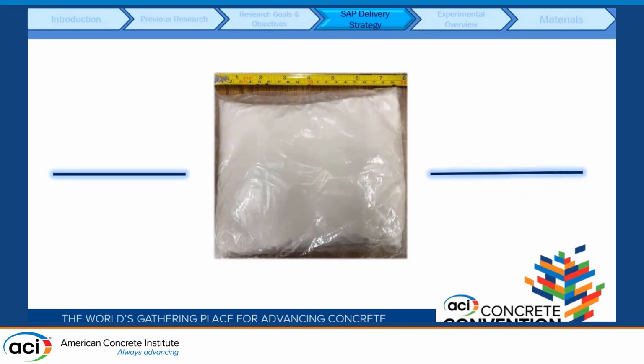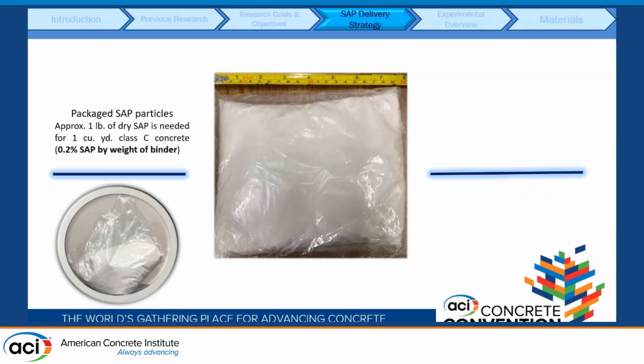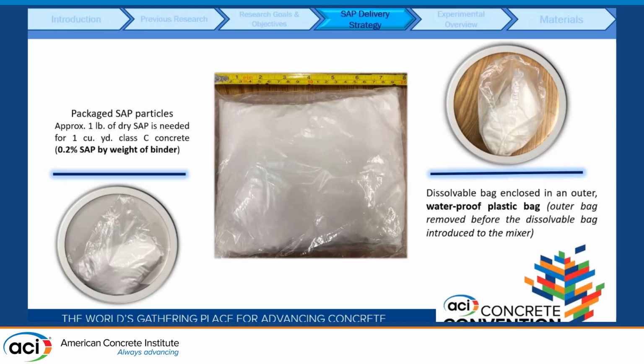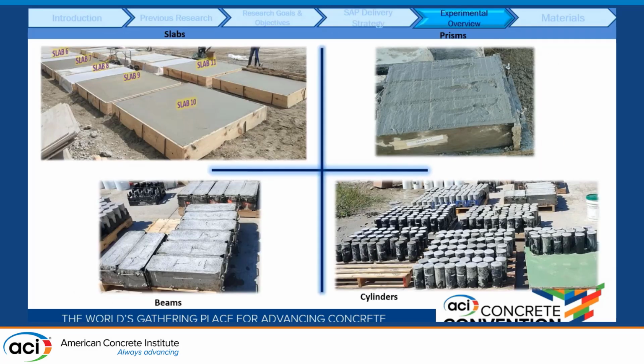For the field implementation, we use the commercial SAP, which was packaged in 1 pound dissolvable bags, and these bags are equivalent to 1 cubic yard of concrete. And for storage purposes, the dissolvable bags were stored in a waterproof bag, and the outer waterproof bag was removed before batching. And for the field trials, we cast 6 slabs, 8 feet by 8 feet by 10 inches, and we did some beams for flexural strength, as well as shrinkage, some prisms for drying shrinkage, as well as some cylinders for compression testing.